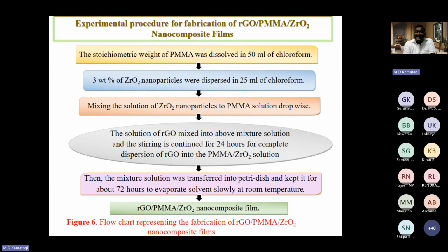And then by taking this reduced graphene oxide, we have synthesized a nanocomposite film, that is a reduced graphene oxide, polymethyl methacrylate, and ZrO2 nanocomposite. The stoichiometric calculation was done, and we fixed 3% of ZrO2 nanoparticles, and we varied the RGO. The ZrO2 nanoparticle solution was mixed into the PMMA solution dropwise. In the meantime, the solutions of RGO of known weight percentage were mixed into the mixture of PMMA and ZrO2 under constant stirring for 24 hours to complete a dispersion of reduced graphene oxide into the PMMA and ZrO2 solution.